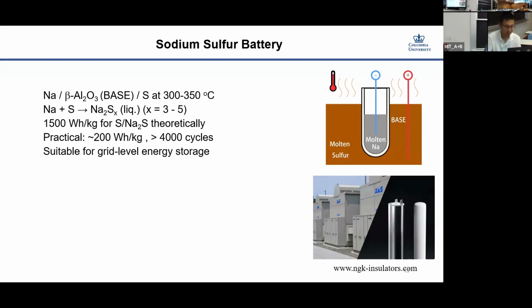because if x is, for example, 2 or 1, then the phase will become solid. And at 300 degrees Celsius, this solid phase doesn't have good kinetics, so it's not very productive, and you cannot utilize the capacity. If you are limited to x of 3 to 5, you get very good cycle life. And because of the low cost, it's suitable for grid-level energy storage.